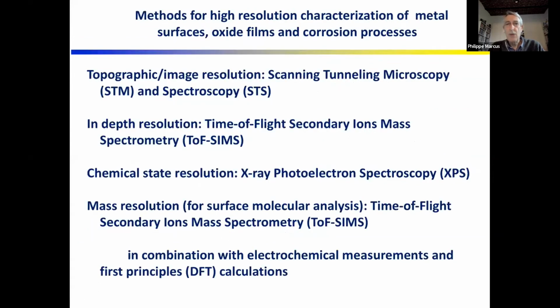To look at these problems, we need methods for the characterization of metal surfaces, oxide films, and corrosion processes. We need high resolution methods if we want to understand the initiation of corrosion. If we want high image resolution, we use scanning tunneling microscopy. If we want in-depth resolution near the surface, we use time-of-flight secondary ion mass spectrometry. If we need good chemical state resolution to investigate the nature of surface oxides or surface compounds, we use X-ray photoelectron spectroscopy. If we want mass resolution, which is very important if we study molecules at surfaces like organic inhibitors, we again use time-of-flight secondary ion mass spectrometry.